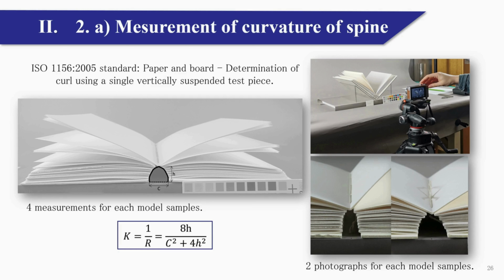The first step in characterizing the properties of each model type is to compare the arc formed by the spine when the book is open to 180 degrees at its central bifolio. The arc is measured according to the determination of curve standard to calculate the curvature of the spine. We measure the chord C and the height of the spine H, as you can see on the diagram. Then we put the data measurements in the formula to calculate the magnitude of curl called K. To evaluate each arc, we establish an ideal K value of 83.3, which corresponds to a perfect semicircular arc. A standardized photography protocol was carried out to compare visuals and quantitative data.